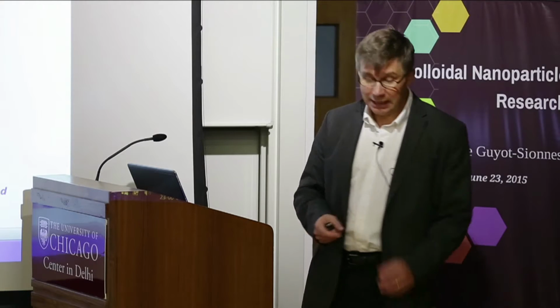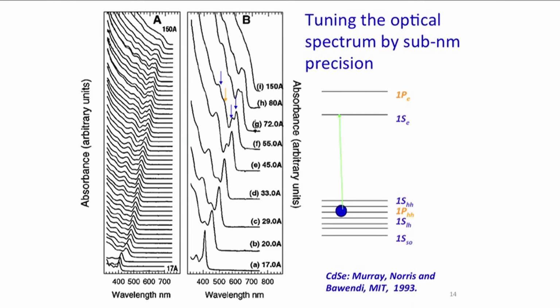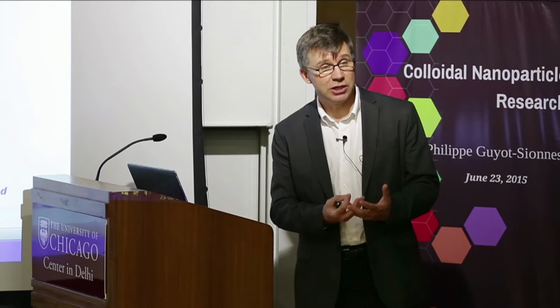The fact is that it works beautifully, and this is the work by the MIT group from 1993, probably the most significant paper in that field, where they showed this exquisite tuning of the color of the nanoparticles simply by changing the size. And so here they were going from 17 angstrom to 150 angstrom of particles controlled at the sub-nanometer resolution. And you can see the color changes. Now normally, in chemistry, if you want to change the color, you have to change the composition.